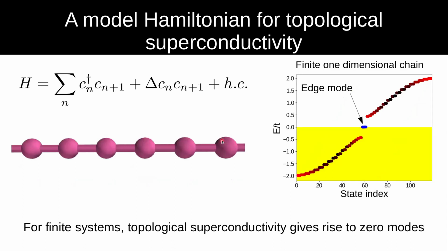The most interesting thing is if you look at this very same Hamiltonian, not in a periodic system, but in a system with open boundary conditions. So on a chain that has 100 sites, for example, where the first site is not connected to the last. If you do the calculation of the electronic spectra in this case, what you actually observe is that you have a gap for most of the states, but there are some states that are exactly pinned at zero energy. And if you look at the location of these states, you see that they are located on the edge. These modes are the topological modes of the superconductor.